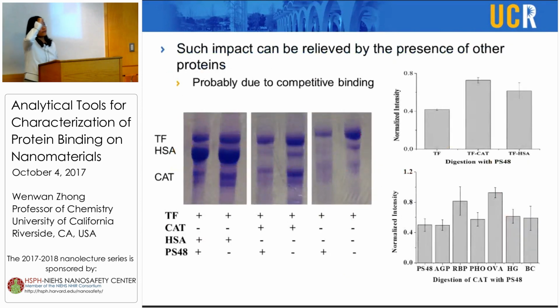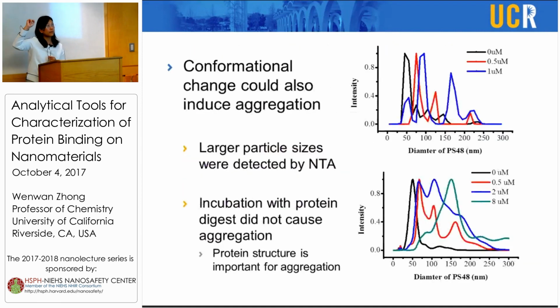And here, if we have other proteins in the mixture, because they compete for the same binding site on the particle, it could alleviate this susceptibility to protease digestion. So due to competitive binding, this again agrees with the protection model. If you have other proteins to protect the surface and prevent binding of certain proteins, then the conformational change of those proteins would not be observed anymore.